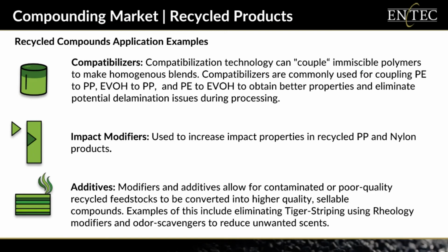So here are a few application examples of how we can salvage recycled products using modifiers and additives and prevent them from being sent to a landfill. Compatibilizers are a specific type of additive that helps to couple or tie together dissimilar or incompatible materials to make a homogeneous compound. For example, compatibilizers can be used to couple PE contamination and polypropylene. And as most of you are probably aware, it is not uncommon to have PE contamination in PP feedstocks. And while a small amount of PE is okay, higher percentages are unacceptable and can lead to poor properties and delamination during injection molding. Adding an olefinic block copolymer to the compound can result in complete compatibilization and improved properties.